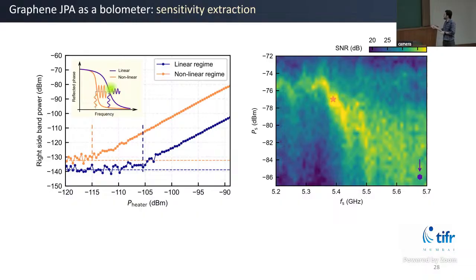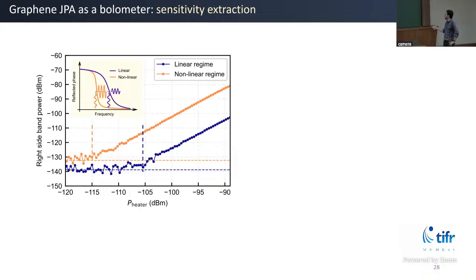That's why you see here a 20 dB enhancement in the signal power compared to the linear regime. That is really important, because you won't get the same feature in other bolometers, since those are mostly linear bolometers. To get any amplification effect, you have to add series amplifiers in your fridge subsequently. But our device is an integrated device. It's a nonlinear amplifier, so it senses and at the same time enhances the signal power, which you won't get in other devices. That was new in our project, and we demonstrated it in our work.